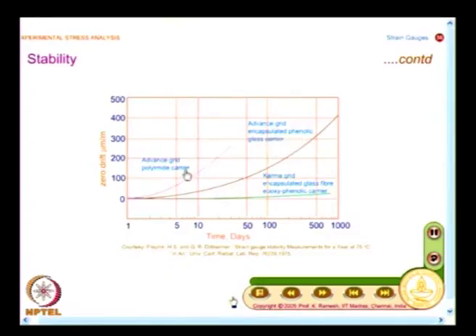It is much better than the polyimide carrier. So, what you find? You see a very significant zero shift in a simple advanced grid with polyimide carrier, which is substantially reduced when I just change the carrier material. And the third graph, which is almost close to 0, that you get from Karma grid encapsulated with glass fiber epoxy phenolic carrier.